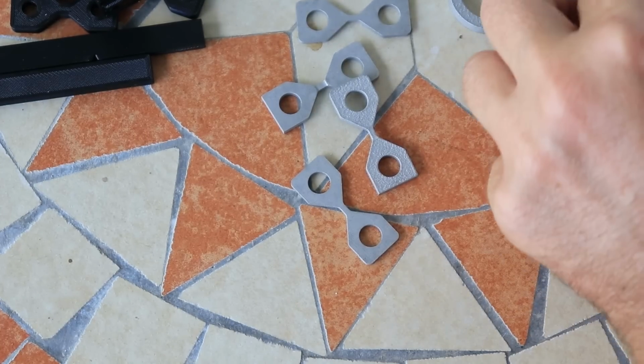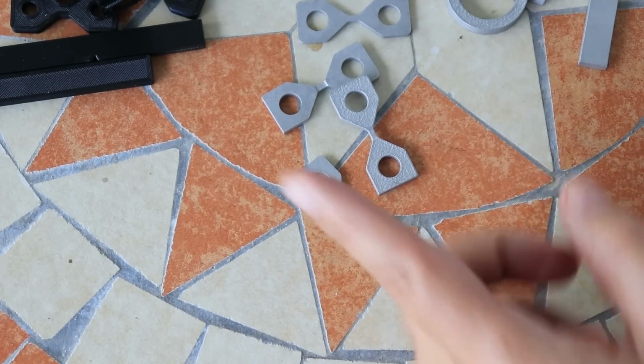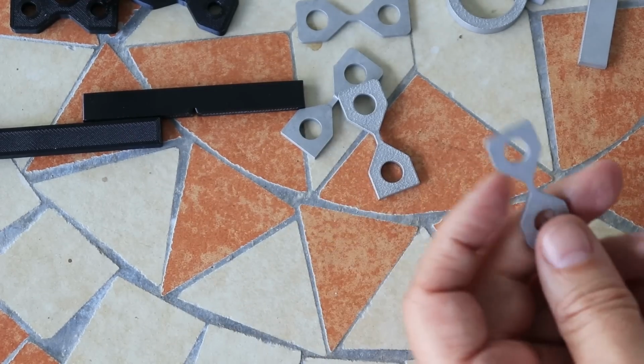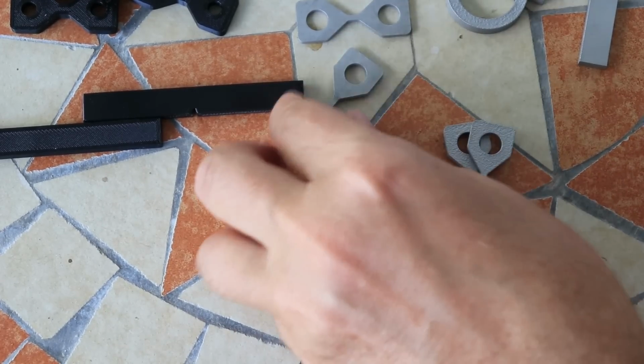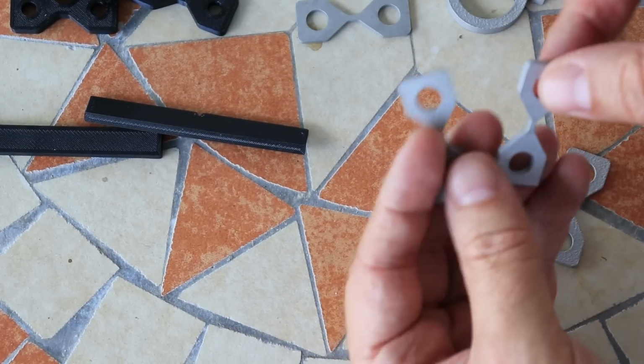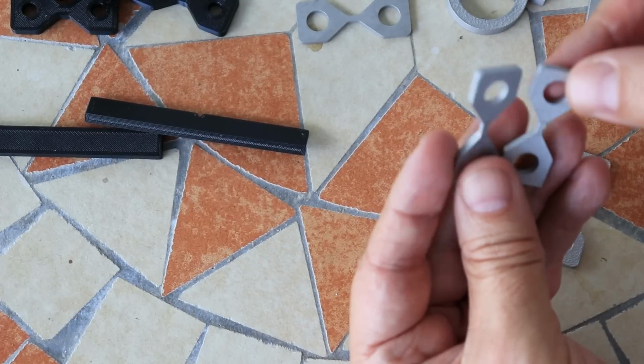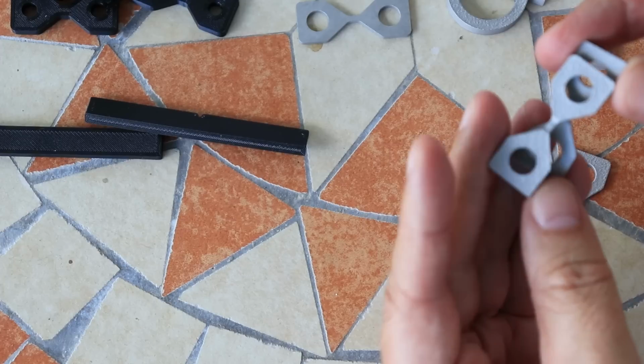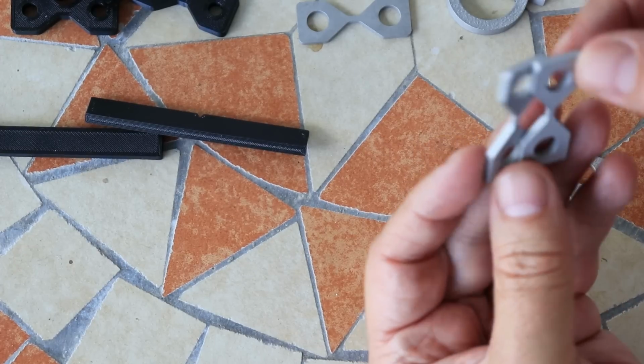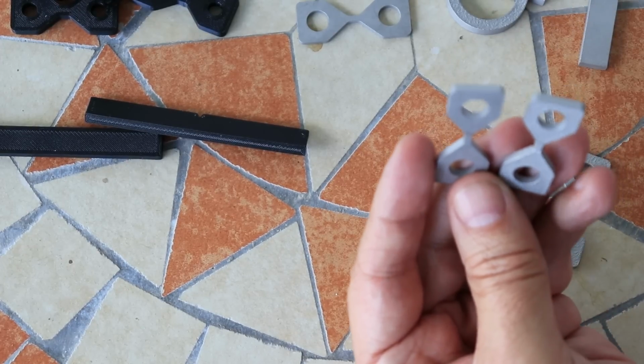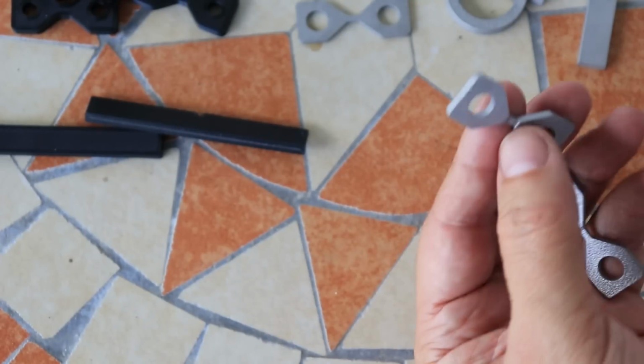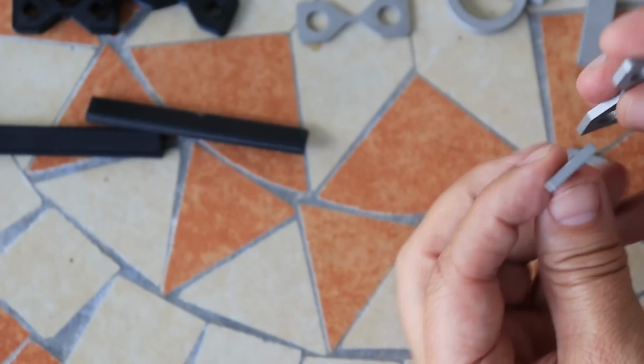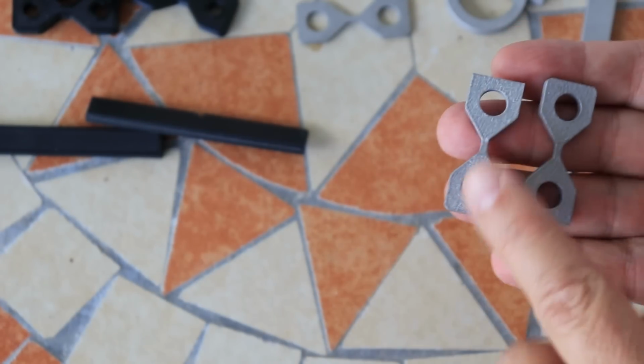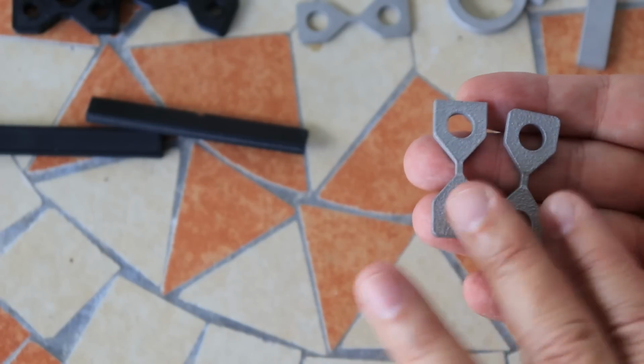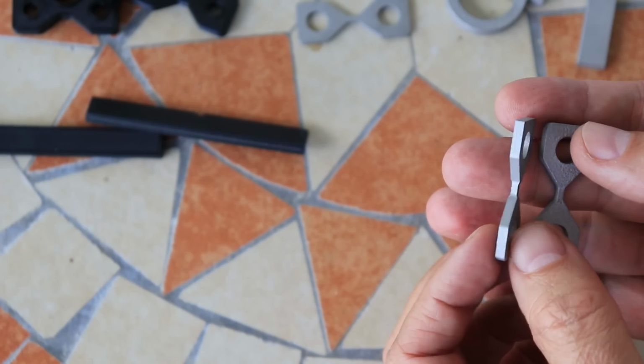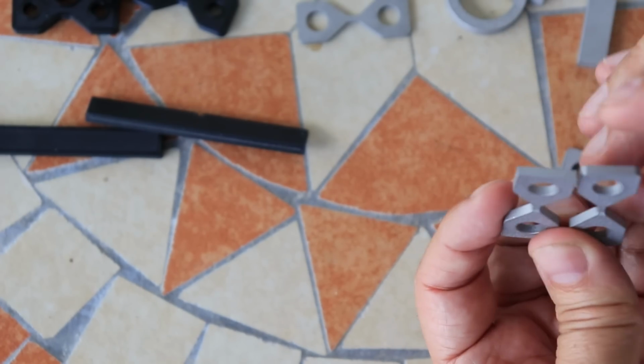4.12. So it looks like the accuracy is actually better than with the ABS parts. And just in case, this is printed in vertical position to see if we have some kind of layer adhesion. But I think they didn't print this in vertical position. 2 by 2 millimeters in the middle, and this should be printed in vertical position, but I can see from this texture that this is printed in horizontal position, so actually I cannot test here the real layer adhesion, but